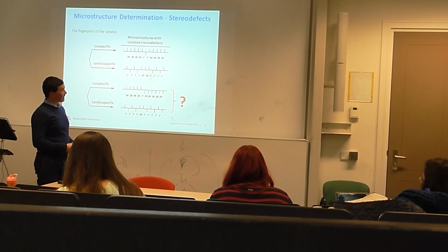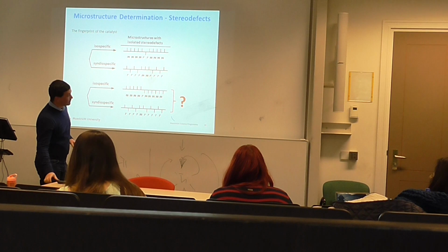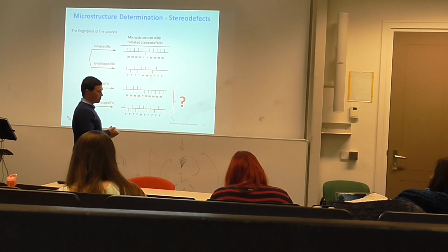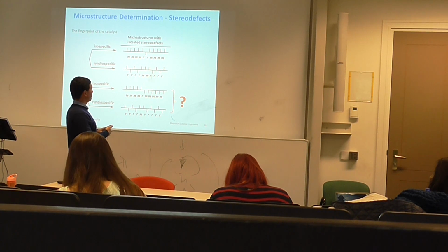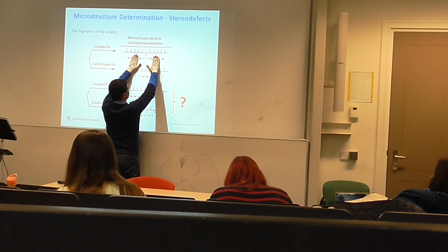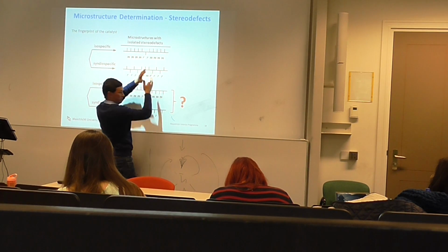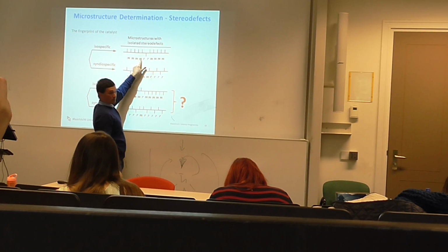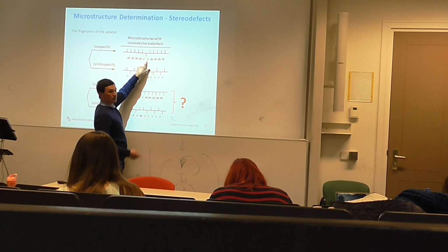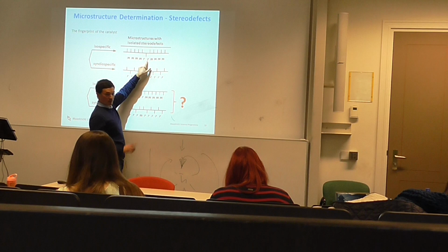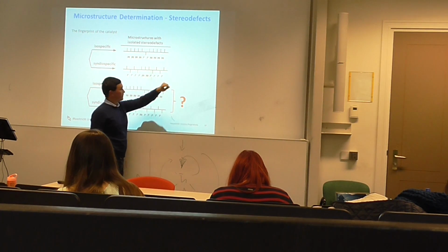So if you look at the pentads, which are 5 methyl groups, you will see something like this. It's a classic stereo defect, MRRM. So a string of M, mistake, R. The site corrects itself, another R because it points up, and then M.